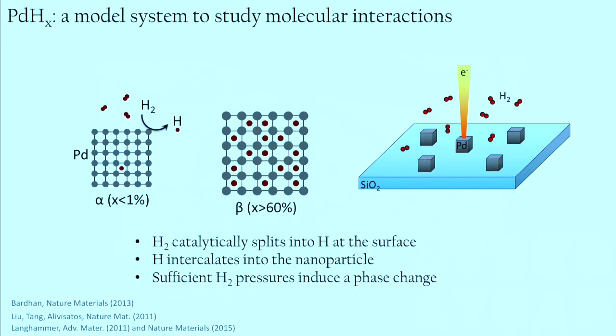So as a model system, when we wanted to benchmark this technique, we wanted to look at photocatalysis, and we figured we'd start off by looking at the hydrogenation of palladium, in part because it's one of the oldest material science systems that's understood, with phase transformations and phase diagrams dating all the way back to the 1800s. So in bulk, it's an extremely well-understood phase transformation. There's less known about how nanomaterials transform, but it turns out the system is actually isomorphic to a lot of the photocatalytic and energy storage devices that you would enjoy today.